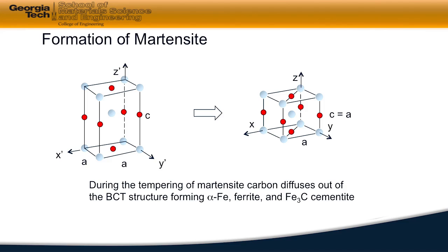So with time at temperature, we relieve some of the stress associated with the carbon being trapped in the BCT structure, and the precipitation of the second phase, namely Fe3C.